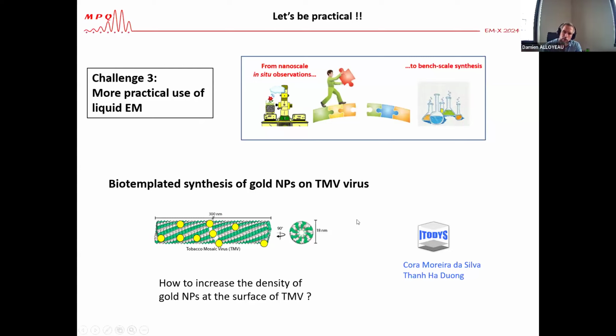And I'd like to show you a collaborative work that we performed with the ITODYS laboratory. We work on biotemplated synthesis of gold nanoparticles on TMV viruses. So biotemplated synthesis is performed to control the distribution of gold nanoparticles in 3 dimensions. And here the idea, my colleagues want to develop a SERS probe. So the idea is to add a lot of gold nanoparticles on those viruses, because when you increase the density of nanoparticles, you increase the plasmonic interaction in between the nanoparticles, which shifts their plasmonic resonance in the biological windows.